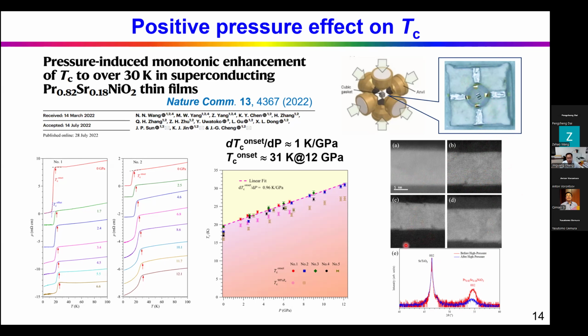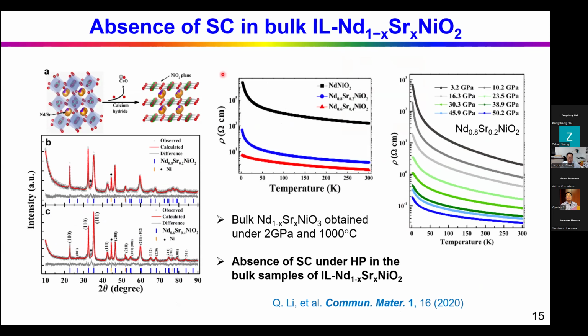So it means that for this infinite layer nickelate, the superconductivity is very sensitive to the structure. You have to keep the structure perfectly in order to reach zero resistivity. This may explain the absence of superconductivity in the bulk infinite layer samples. For the bulk samples, you can see the XRD peaks are pretty broad, and so far superconductivity cannot be found in the bulk samples.